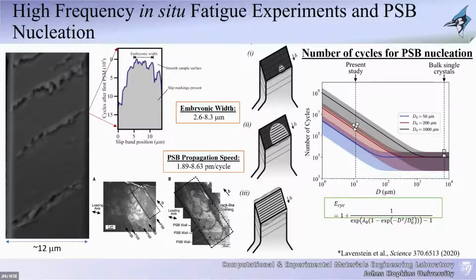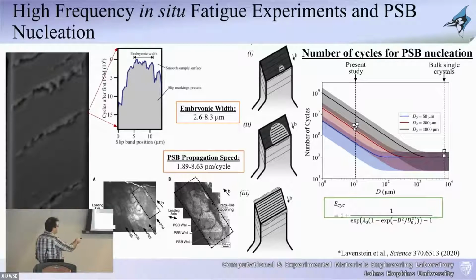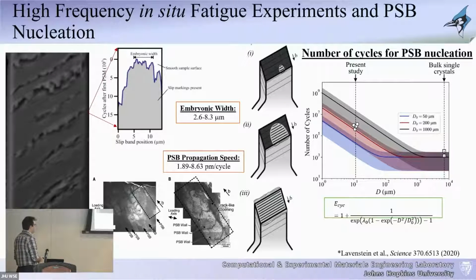So this is, again, another intriguing analysis that we were able to do with this. Through image analysis of what we're seeing on the surface, we could take one of these bands, and as you see, there are 2 features that happen. One of them is that they pop up with a certain width, so we can basically quantify what that width is. And if you go through these analyses of the different experiments that we did, the embryonic width, which is basically the initial extrusion that happens on the surface, seems to range between 2 microns and 8 microns for the sample sizes that we've been looking at.